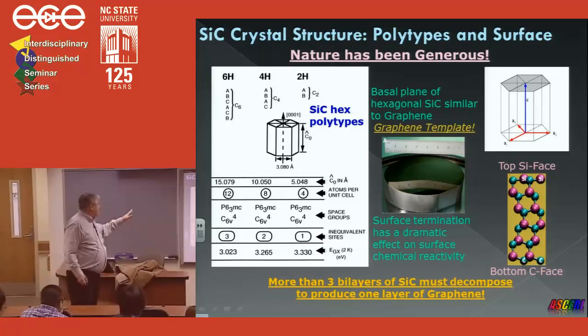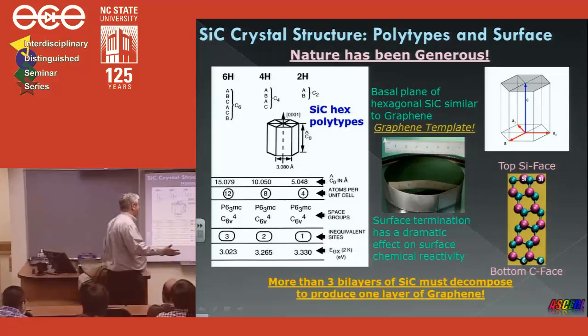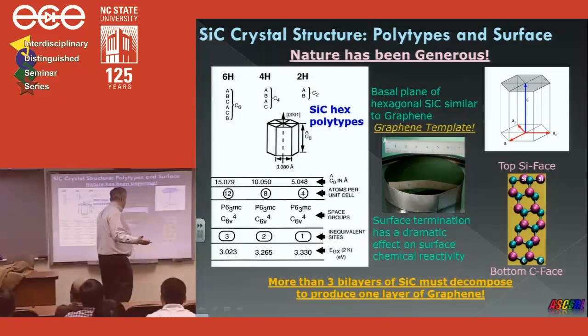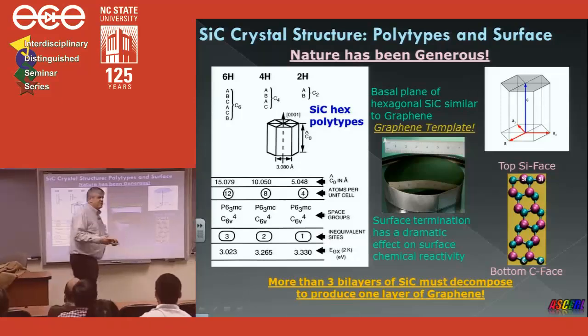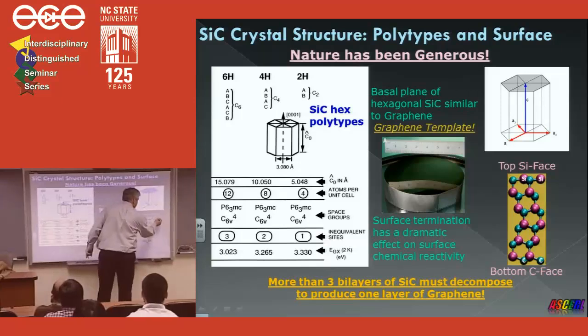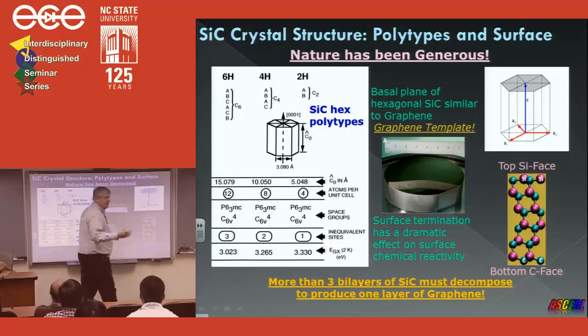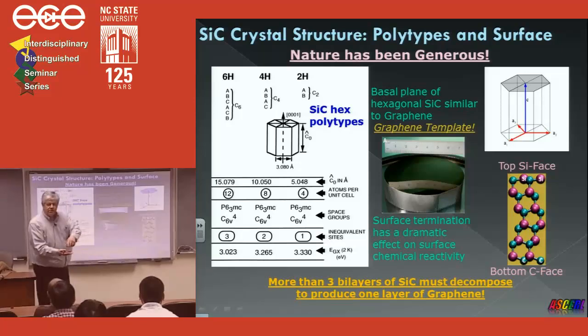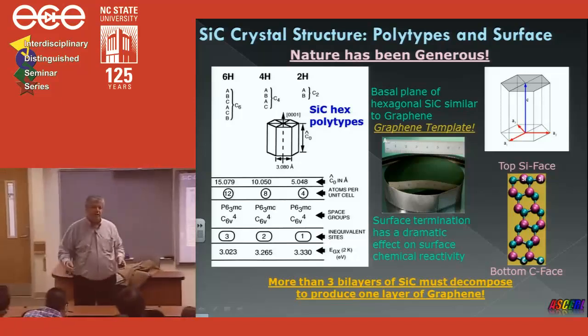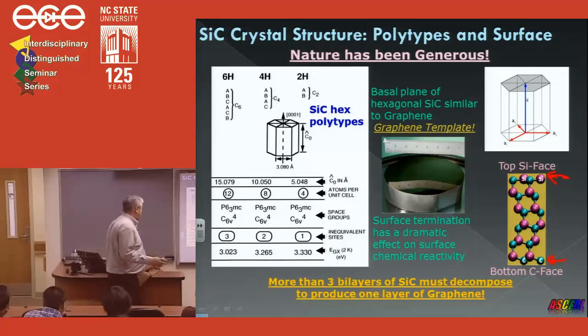Now, because of silicon, we're going to start writing on this now. Because silicon carbide has, what's a great color? How about red? Silicon carbide is a polar material. So one face is a silicon face and the other face is a carbon face. So here's the silicon face and here's the carbon face. And so if you have a wafer, one side will be the silicon face, and if you flip it over, the other side will be the carbon face. And that becomes very interesting because the properties of graphene grown on those two faces are completely different. And you're going to find out more about that in just a moment.